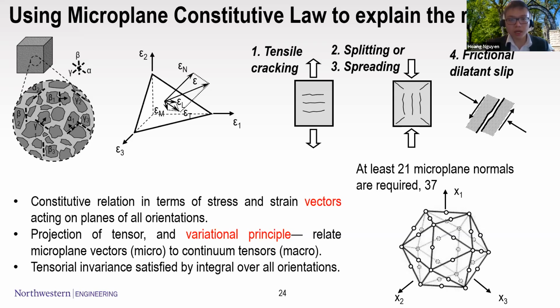So how to explain those mechanisms and the relevant behaviors? We used a model called the microplane constitutive law model, developed within our group, and the model is based on the breaking of the stress-strain tensor into stress-strain vectors onto multiple microplanes. This reflects the fact that in quasibrittle materials, heterogeneity appears, so stress and strain vectors appear on the surface of the heterogeneity. And this model can capture several behaviors, especially in the triaxial stress state that appears at the crack tip: tensile cracking, splitting or the spreading of microcracks, and also frictional behavior and dilatancy.